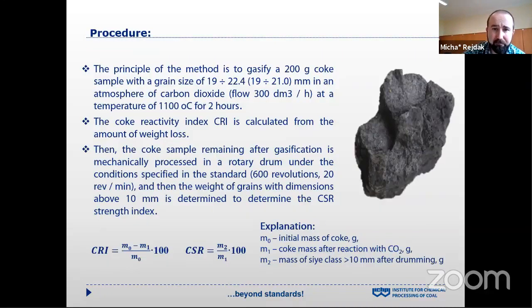The principle of the method is to gasify 200 grams of coke with the proper grain size between 19 and 22.4 millimeters in the atmosphere of carbon dioxide at the temperature of 1100 Celsius degrees. The duration of the process is exactly 2 hours. The coke reactivity index CRI is calculated from the amount of weight loss, and then the coke sample after gasification is mechanically processed in a rotary drum under specific conditions, 600 revolutions with 20 revolutions per minute. And then the weight of grain with dimension above 10 millimeters is determined to determine the CSR index.